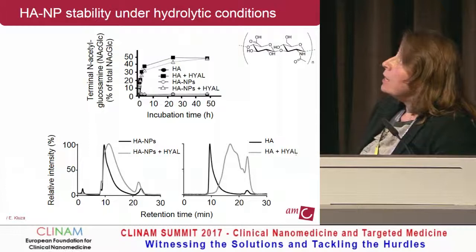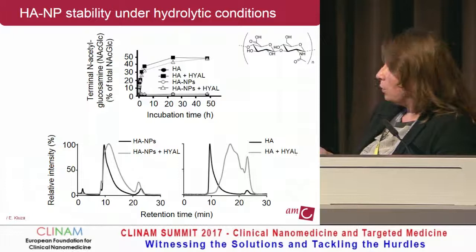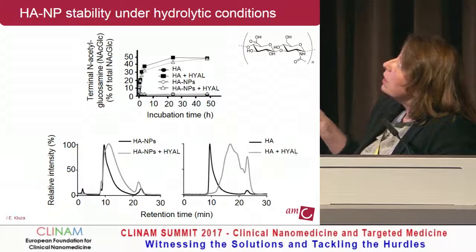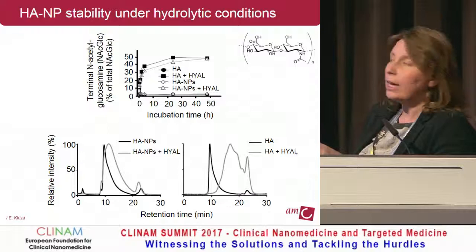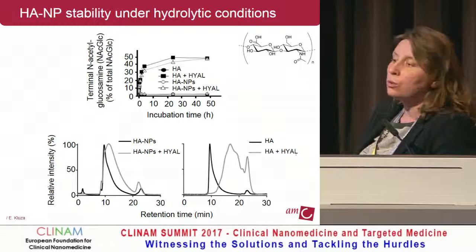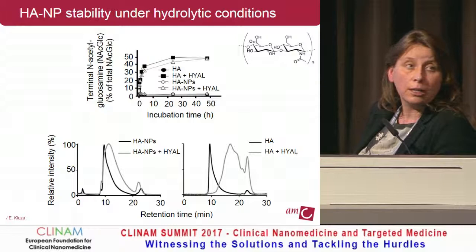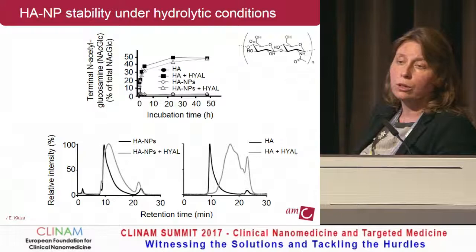We also used a more conventional way to look at hydrolysis. Once we looked at the release of terminal glucosamine — because the enzyme cuts there — we didn't see a lot of differences between non-formulated hyaluronidase and the nanoparticle version. So the enzyme still does the job. But with size exclusion chromatography, the shift in retention time for nanoparticles was hardly present, whereas for free hyaluronan we definitely see the formation of small oligomers.